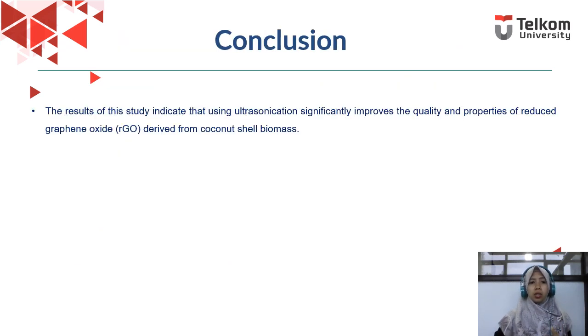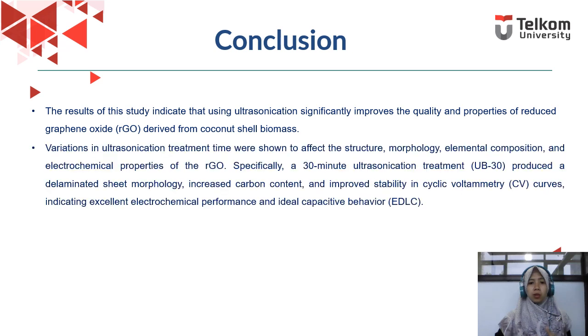The conclusion. The results of this study indicate that using ultrasonication significantly improved the quality and properties of reduced graphene oxide derived from coconut shell biomass. Variation in ultrasonication treatment time was shown to affect the structure, morphology, elemental composition, and electrochemical properties of RGO.